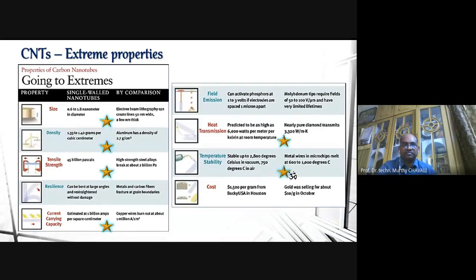If you see some of them highlighted here with a star, for example, the single wall nanotube, the size is going to be 0.6 to 1.8 nanometer, and in the E-beam, it is only 50 nanometers wide. If you take temperature stability, they have 2800 degrees centigrade temperature stability. Metal wires are only up to 600 to 1000 degrees centigrade. If you have polymer composites with metal composites, you can increase the temperature, but at the same time strength also increases. But if you replace these metals with carbon nanotubes, you are going to have increased temperatures and increased tensile strength, which is 45 billion Pascal compared to high strength steel, which is only 2 billion Pascals. Current carrying capacity: highly conductive materials at 1 billion amps, while copper wires burn out at about 1 million ampere per square centimeter.